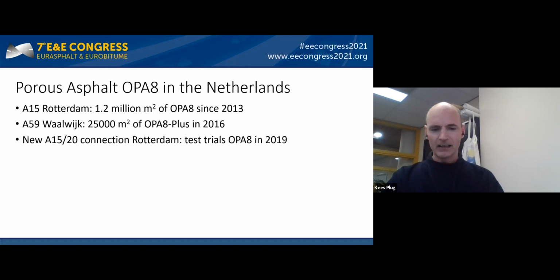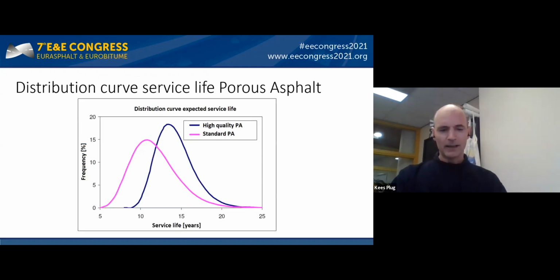The porous asphalt OPA 8 has been used in three projects in the Netherlands. The main project was the A15 with 1.2 million square meters and two little projects with the A59 and A15/A20 connection in 2019. As mentioned, the service life of porous asphalt depends on several factors. This can be illustrated with the distribution curve of the service life. As can be seen in the picture, the average service life of a high quality porous asphalt, the blue line, is higher than standard porous asphalt, the purple line. But partly the service life of both products will overlap. So a high quality porous asphalt can fail early and standard porous asphalt can be better than expected, as can be seen in the picture.